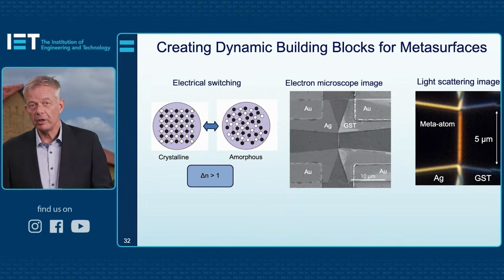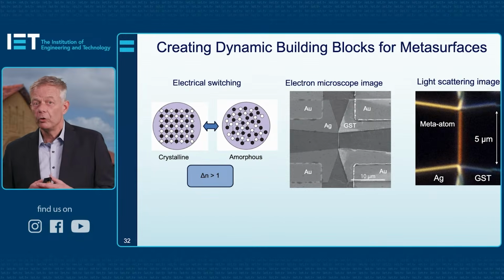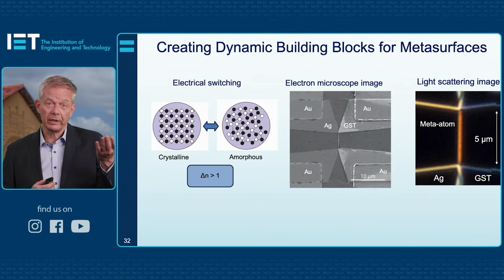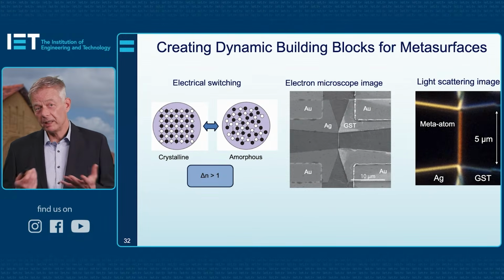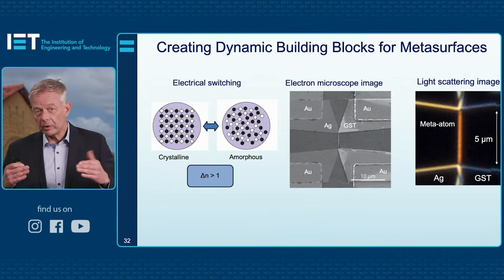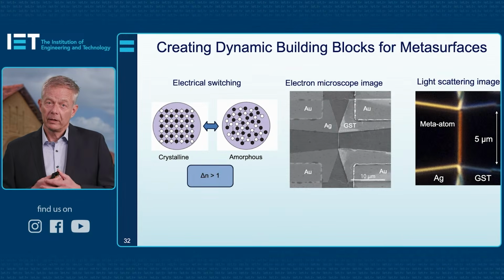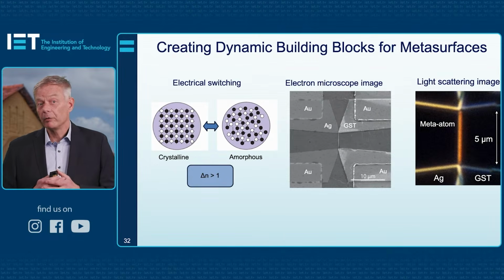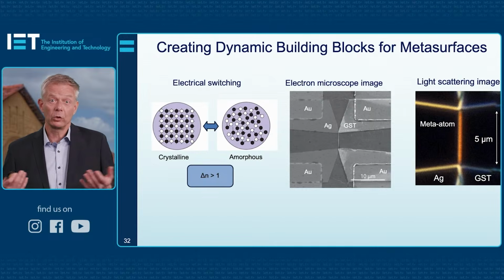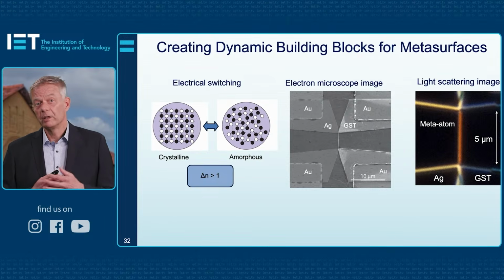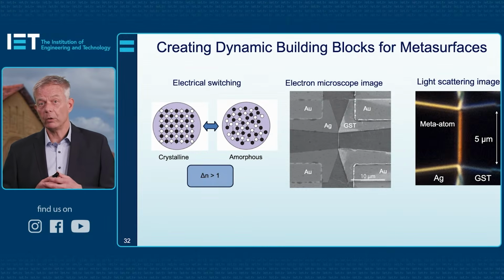This phase change material can switch between two structural phases, a crystalline and an amorphous phase. And the key thing is that these phase change materials allow an order of unity refractive index change between the two phases. That notably can allow us to tune the scattering properties of the nanowires.